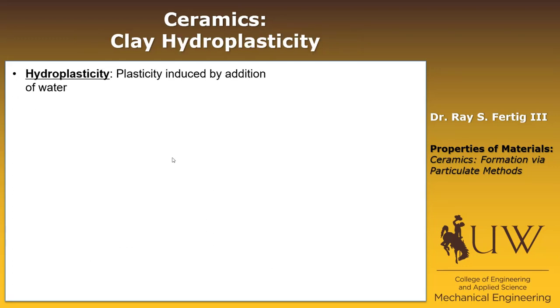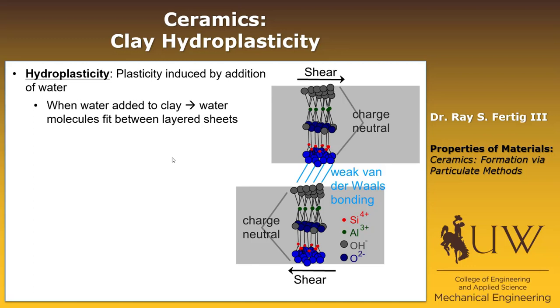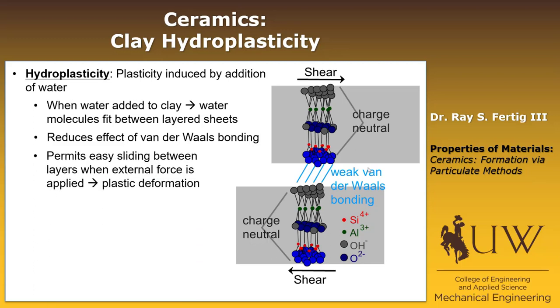Another method requires us to understand something unique about clays called hydroplasticity — plasticity induced by the addition of water. When water is added to the clay, remember that clay is structured as alternating layers of silica and alumina. The water molecules fit in between those layered sheets, bonding between them and weakening the Van der Waals forces. That reduces the effect of Van der Waals bonding and allows easy sliding of one layer relative to the other when any external force is applied.